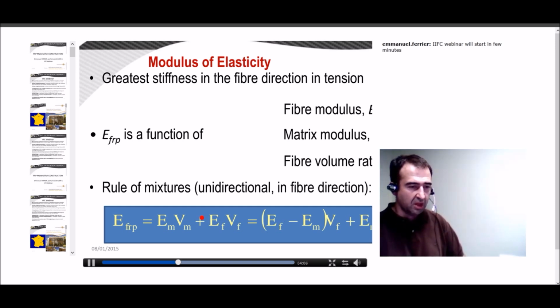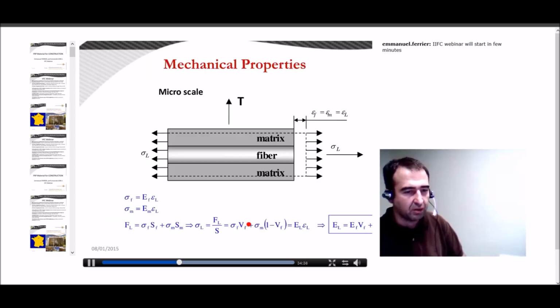the carbon, for example, Young modulus, which is nearby 200,000 megapascal. If we compare it to that of a usual epoxy, it is only 3,000 megapascal. So the difference is nearby 100. So the mechanical properties of your FRP will depend on this value and of course this one. If your ratio is very low, your final properties will be very low also.